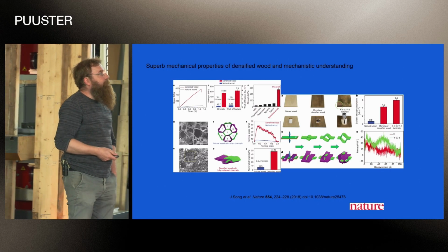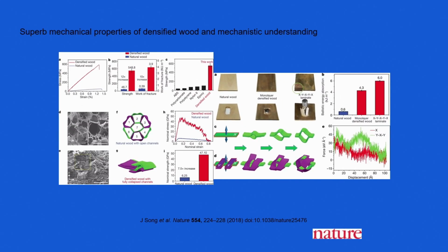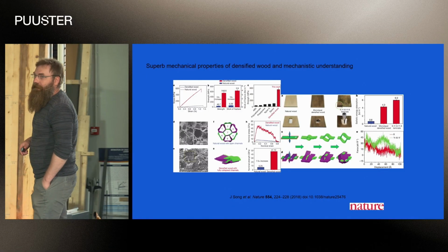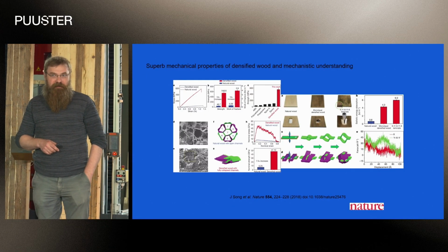And for example, here's a strain stress curve of a natural wood. We are having here on the scale bar, here is 200 megapascals. If we look at the natural wood or densified wood, we see that the mechanical properties increase quite a lot. We are talking about here strength increased up to 12 times in this article and 10 times increase in the work of fracture. They did also some ballistic tests on this, and basically one can produce almost bulletproof wooden materials with this densification.